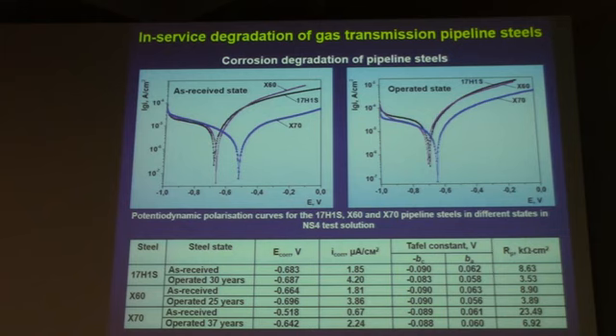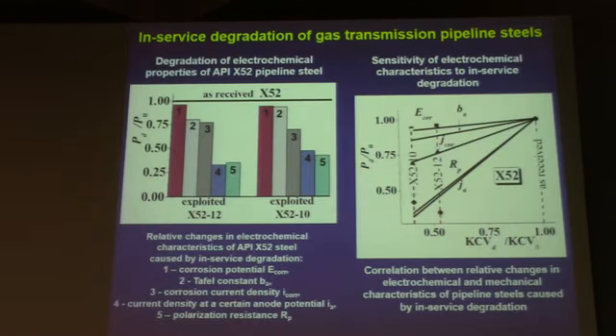for the degraded steels. Deterioration of a number of electrochemical characteristics indicated the corrosion degradation, which obviously was caused by in-service degradation due to a long-term mutual effect of working stresses and corrosion hydrogenated environments. And electrochemical characteristics have different sensitivity to in-service degradation of material. So it's important to compare the relative changes in them for the same degradation degree.